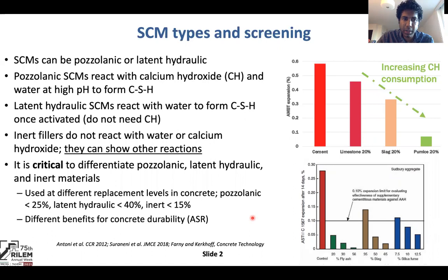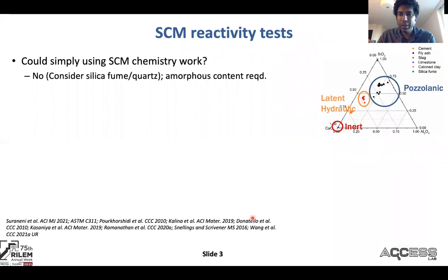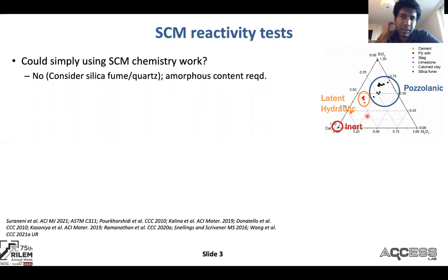So again, how do we screen or measure the reactivity? Very simply, could using the bulk SCM chemistry work? You see there is some clustering of latent hydraulic, inert, and pozzolanic materials, but the answer is absolutely not. The bulk chemistry does not work — it's a terrible idea. Consider silica fume versus quartz: they're both 95%+ SiO2, one is reactive and the other is not, because it is the amorphous content which controls the reactivity.